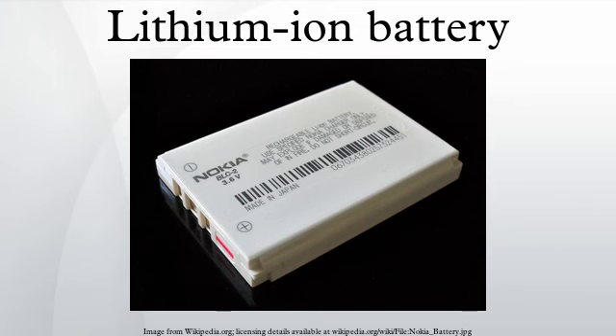Short-circuiting a battery will cause the cell to overheat and possibly to catch fire. Adjacent cells may then overheat and fail, possibly causing the entire battery to ignite or rupture. In the event of a fire, the device may emit dense irritating smoke. The fire energy content of cobalt oxide cells is about 100 to 150 kJ per Ah, most of it chemical.